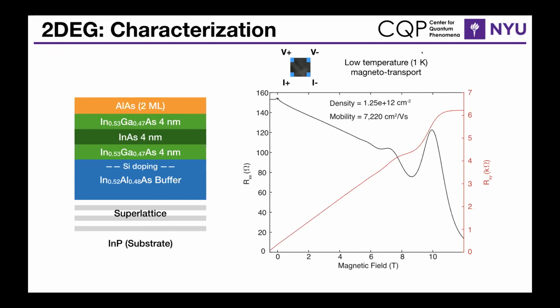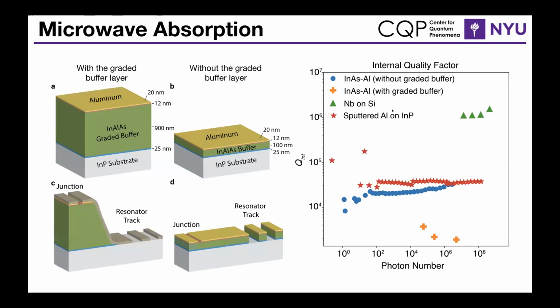So we conducted low temperature magnetotransport on this sample at 1 Kelvin, and we saw that you can actually get an electron density of 1 times 10 to the 12 per centimeter squared. Electron mobilities that are exceeding 7,000, and you're starting to get these well-defined quantum Hall states, which signify that you just have a nice 2D channel for your electrons. So up until this point, we're able to say that we can grow good quality, relatively good quality 2DEGs, and we're able to grow aluminum layers on indium arsenide without this huge reaction.